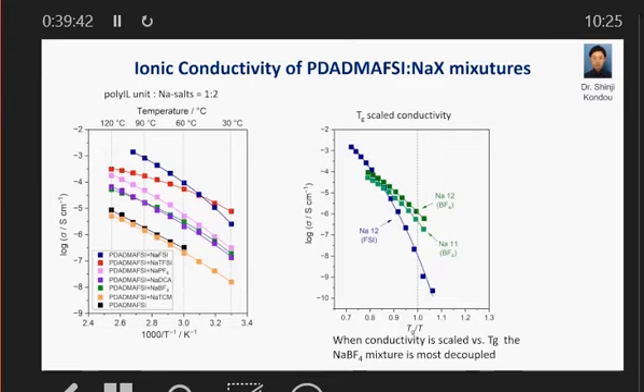The interesting thing here, going back to what is a transport mechanism, on the right-hand side, we scale the conductivity by Tg to see whether or not the ion conductivity was coupled to the polymer Tg. And what we see is that in the BF4 system, at Tg over T equals 1, that's where your system is being measured at its glass transition temperature, we're actually measuring higher conductivity compared to what you measure in FSI. And this correlates in Austen Angell speak to a decoupled system.